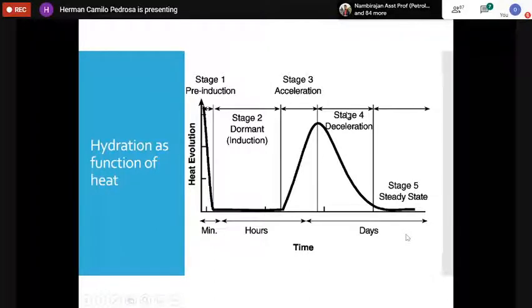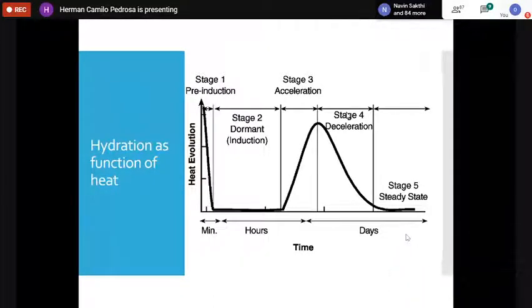Usually in a cementing operation, there are a few things that are very important. One is the time that the cement will be fluid. This will be the dormant part, because that is the time that a cement engineer will have to conduct the cement operation. And then the other important time will be the steady state, when it has reached a certain strength. Because after we place the cement, the well should be shut down so they can give time for the cement to set. Usually it can take between some hours, let's say 6 hours, to even a couple of days. It depends on many factors.